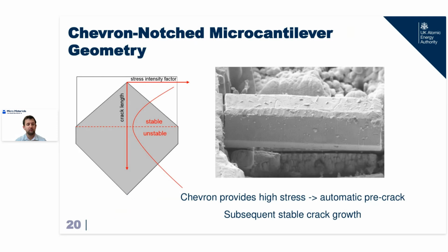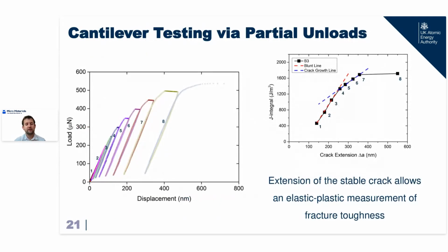So you don't have to worry about FIB damage in your crack or whether your crack is sharp enough for valid fracture toughness measurements. The other nice thing is that, because your cross-sectional area increases, that stress intensity factor drops, and you get very stable crack growth, and you can study that as your crack grows very slowly through your cantilever. And this is quite nice especially for tungsten, which is just about plastic enough not to show full